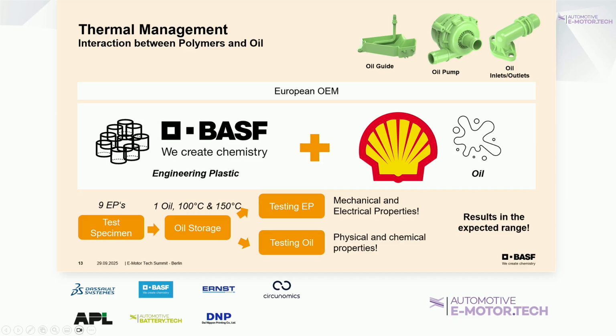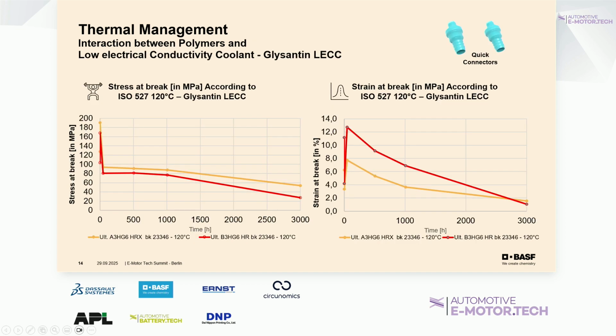At the end of the day, I could say we made this big study and there was no real surprise. The results were all in the expected range. But still it is important to know, if we also talk about combinations with coolants, that you have a kind of influence. So especially with polyamide, PA6 and 6.6, there is an influence. For example, here you see also overaging. For example, here 3,000 hours, stress at break. So you see a slight decrease. So there is an influence which is important to mention, especially during the design of the part.